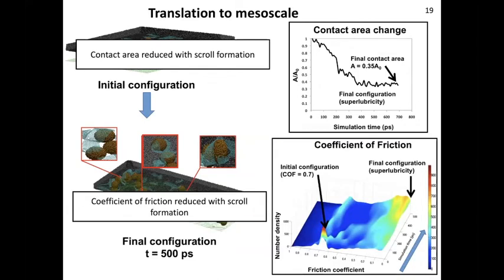65% of this reduction helped us actually to go to the superlubricity regime. If initially, during the zero simulation time, most of our frictional systems were in this unscrolled state with a coefficient of friction of 0.7, then with simulation time, we had more and more systems combining together and getting to this final configuration of zero coefficient of friction.